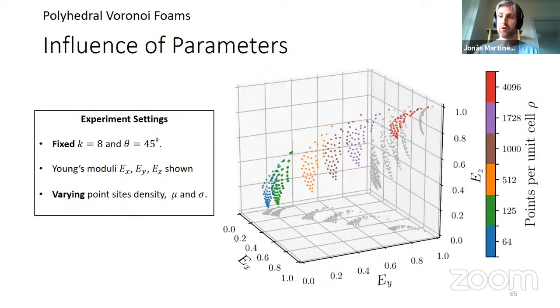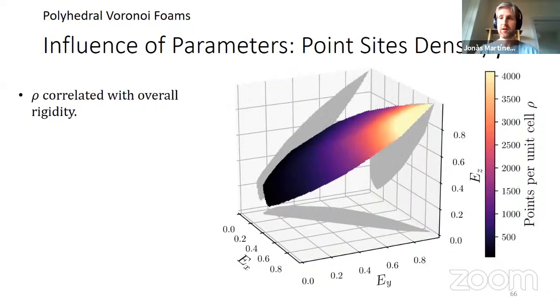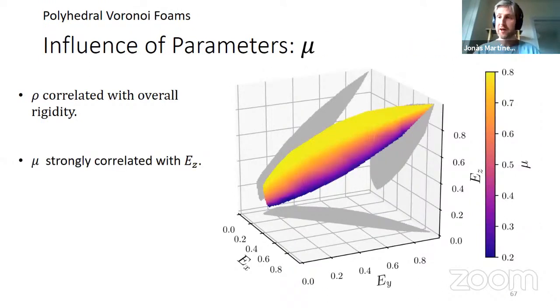So here you can see a plot of the three-dimensional Young moduli in all the three axes. And you can see that there are different spreading families that correspond to different densities and parameters. So as you can see, we span, I will not say a wide space, but we span a continuous space of behaviors. And we can continuously transition from points in this space. So basically, that's something interesting. And we see also that there's a strong correlation between the parameters and the elastic behavior.